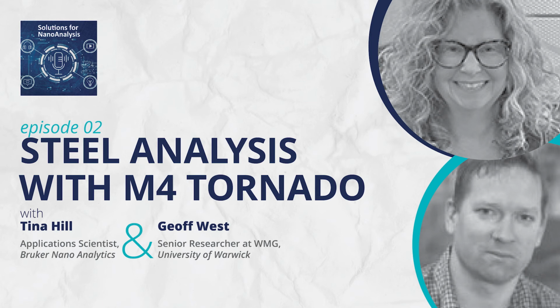And what does that tell you overall? Let's say, are you looking for less homogeneity or less inhomogeneity or more for something like the casting? So as a general rule, steel manufacturers like things to be homogeneous. But I think it's more a case of understanding it because things don't stay cast forever. So once they've cast it, then they do their forming processes. But it's important to understand what it looked like in the as-cast condition. And then you can see how that compositional variation changes during the processing.